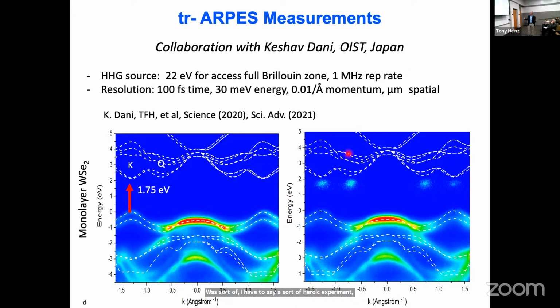But this is the exciting thing. We actually see electrons that are in the range of the predicted conduction bands. And this was taken at some delay time after we photoexcited the system. So we expected to have electrons here, which is the direct band gap. We actually weren't so sure that we'd have electrons over here in a different valley in the Brillouin zone. Certainly, we didn't excite them there. We had the vertical excitation. So this is clearly a signature of excited electrons.